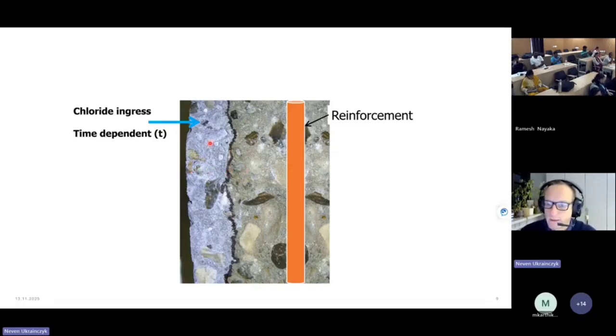And this is the RCM test. When you spray it with silver nitrate after diffusion, you can see the silver chloride in this silver color. So you can exactly see the penetration depth, how the chlorides come in, and you can see here some ITZ effect and aggregates effect.